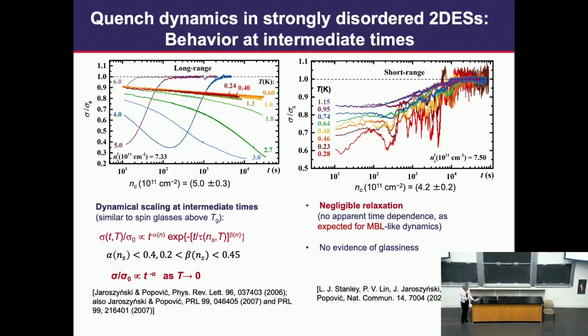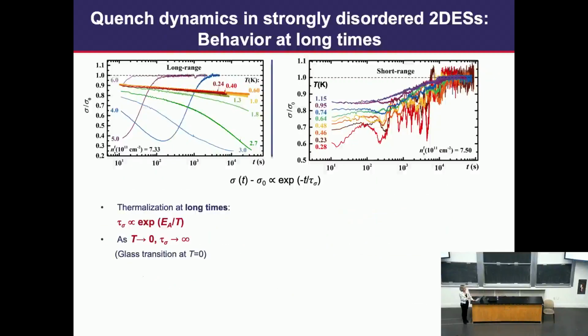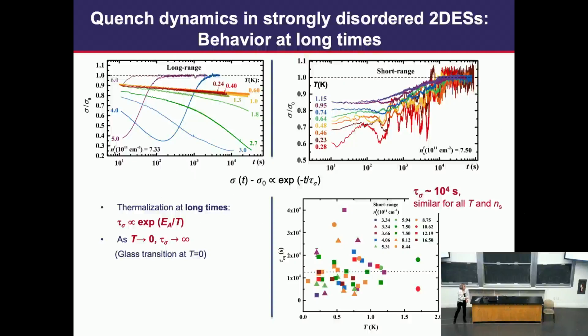But the most striking difference is what happens at long times. I showed you that as you reduce the temperature in the glassy case, it takes much longer to reach thermal equilibrium. But here, all of these curves seem to reach equilibrium at roughly the same time. We analyzed this — it's also a simple exponential process — and extracted thermalization times for different densities and temperatures, finding basically no systematic dependence. Instead, all of the results are scattered around a time of about 10,000 seconds.